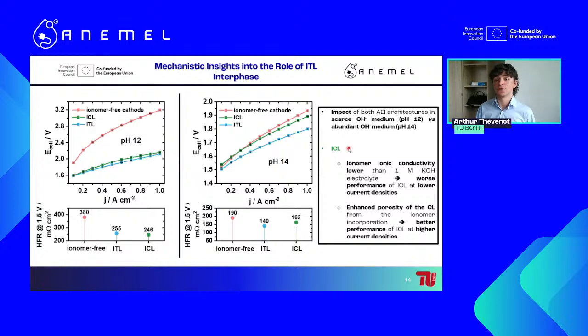Well, starting with the ICL, the first one that we tested overall for this study, we see that at lower current density, we have a worse performance compared to the ionomer-free cathode. This can be explained by the fact that the ionomer ionic conductivity is lower than that of the highly conductive electrolytes, and therefore it will have this lower performance. However, at higher current densities, when you have a bigger flow of these charged species, the enhanced porosity of the catalyst layer, from the incorporation of the ionomer, can then explain the better results that we obtain over here.